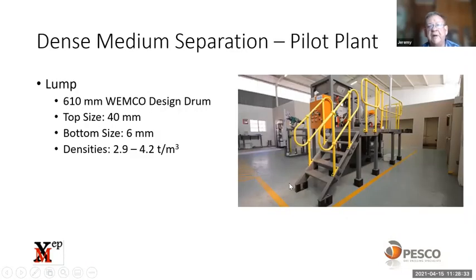If we now go into the pilot plant and look at dense medium separation for the lump, this is a setup that we have at PESCO. We have a WEMCO design drum. It can handle a top size of 40 millimeters, a bottom size of 6, and can handle densities from 2.9 up to 4.2, depending upon the medium grade that you choose.